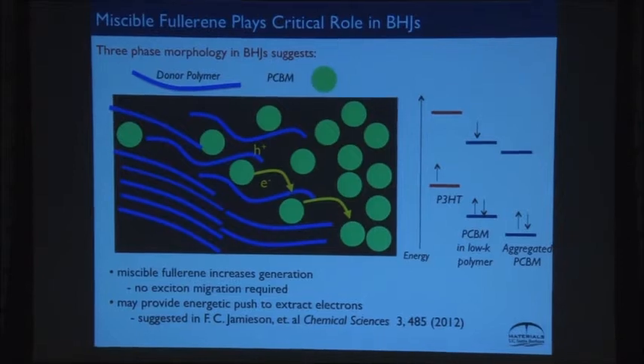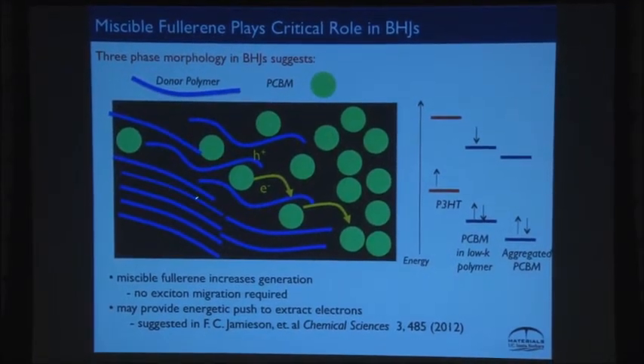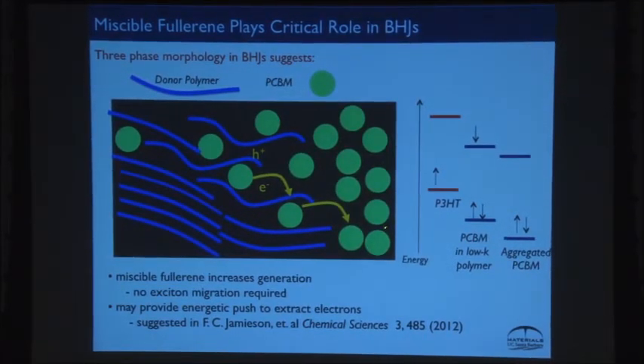It was first put in print by the Imperial group, where if I have a polymer domain here and I have a fullerene domain here and a little bit of mixed stuff, you can do some measurements and convince yourself that the transport levels of the fullerene, when they're mixed in here, are going to be a little different than the aggregated amount, because the dielectric constant is a bit different in there. And so there might be this benefit of having this mixed fullerene, that effectively you're pushing the charge out as long as you have some aggregated network to go there, and it'll slow down the recombination. Okay. Now, we don't know if this is true, and there are arguments pro and con on this.